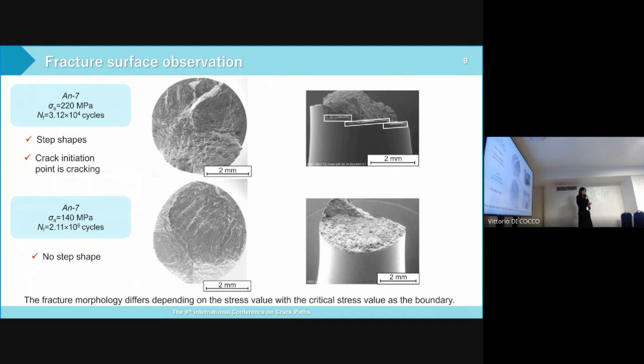AN7 exhibited different fracture morphology above and below the critical stress. The upper figure shows the result of sigma a equal to 220 megapascal, which is the high stress amplitude range. As a result, step shapes were observed similar to those of AN20. So the fatigue fracture initiated from cracking at the fatigue crack initiation point. Next, this is the result of sigma a equal to 140 megapascal, which is the low stress amplitude range, where no step shapes were observed. So the fracture morphology differs depending on the stress value, with the critical stress value as the boundary.